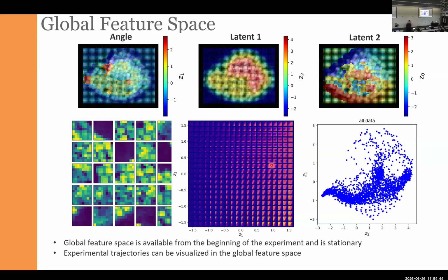Obviously when you construct the latent spaces, you need to pay attention to how good the reconstruction loss is. For example, these are the patches. This is the latent space. You can clearly see that in this case, the reconstruction loss is very high. Our latent space captures things like edges or the presence of the double layers based on intensity. So these are double edges. These are the edges between the double layer and single layer. These are the edges between the single layer and the empty space. It sort of learned how to identify corners, but of course it doesn't capture the much smaller details. So it doesn't have sufficient expressive power.